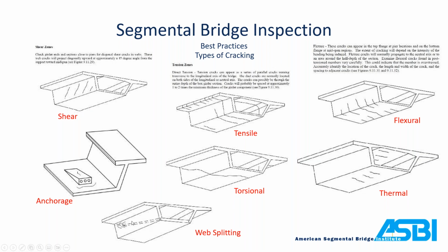Web splitting, this is fairly unique. You might see some spider cracking here around continuity tendons. Torsional, again, it's especially structures on a curve. You may see some torsional cracking, and it may not be continuous. You may see what seems like a shear crack, but then you have some bottom slab cracking that's abnormal or not in a tensile zone or maximum moment zone.